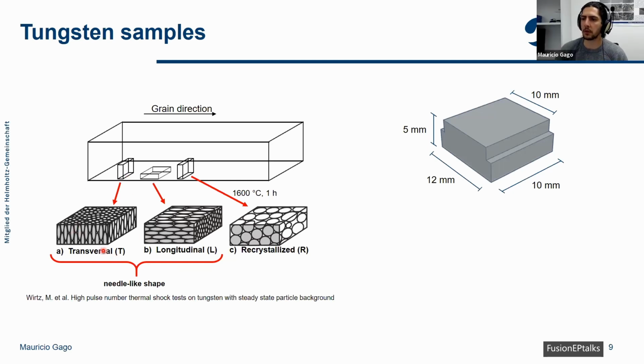Yeah, so in previous tests, other researchers have tested all three structures, and from what I know, no real difference in crack formation has been seen between transversal and longitudinal. So if there is a difference, it's not really that significant. In the end, the decision that was taken to use the transversal microstructure was just because of how the cracks, once they form, expand.